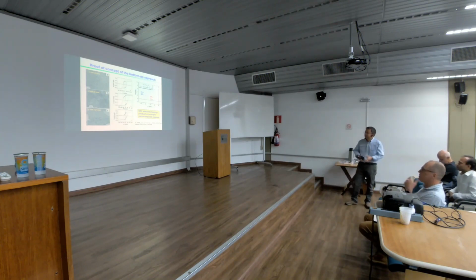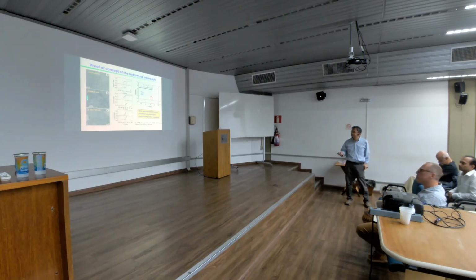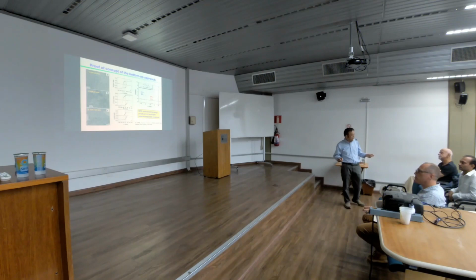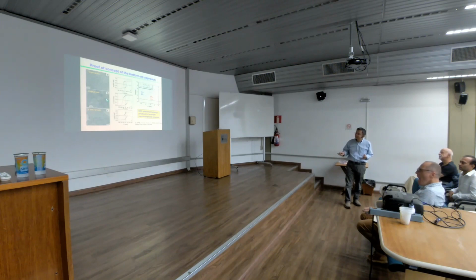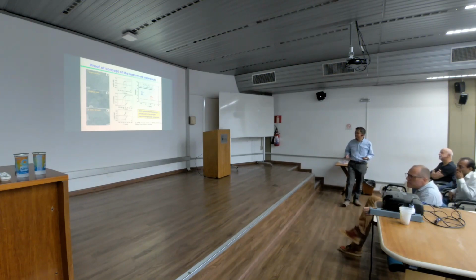And that's the first time we proved the concept of how important the effective exchange coupling between the two phases is, and how homogeneously you have to mix them. Even in this small scale, the homogeneity affects the effective exchange coupling. I told you the story where I started the business. The grain size was 30 micron, 30,000 nanometers. Now we go down to several nanometers. That's the progress.